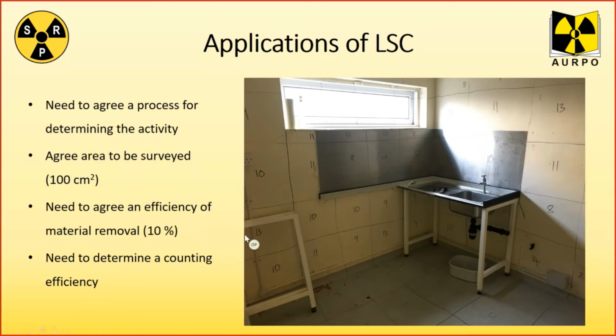When you're doing any sort of wipe testing, you need to make sure that you have a process that's agreeable with you, and you might also have to consult the Environment Agency to check that they're happy with the method that you're using. But you can also consult British standards and those sort of things. You need to work out what sort of area is to be surveyed. If we're doing typical swabs around the lab to check for contamination when it was in use, we would use a 10 by 10 centimetre square area, and we do those routinely. So you'd have 100 square centimetres. But in this case you can see that the grids which have been put on the walls are much bigger, because of the area that we needed to survey.